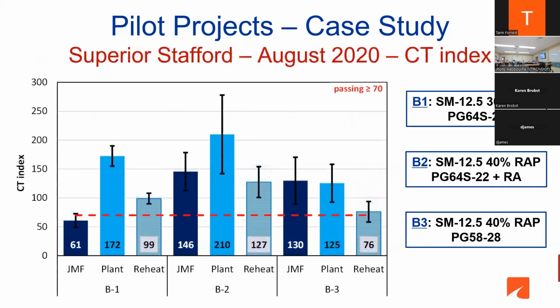The third one, which is usually the most critical for Virginia, is cracking, and that's the hardest to deal with. So we do the cracking tolerance CT index value. The higher the value, the better your mix is in terms of resistance to cracking. You'll see that with the design, your control had a very low value, even not meeting the spec, while the others had much higher values. That means these mixes are expected to be better in terms of resistance to cracking.